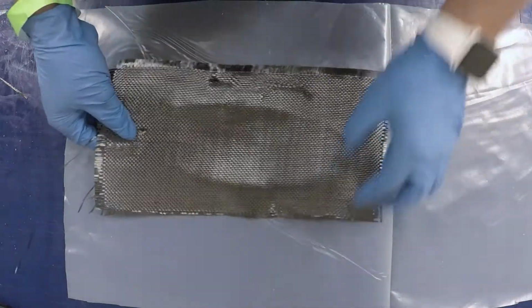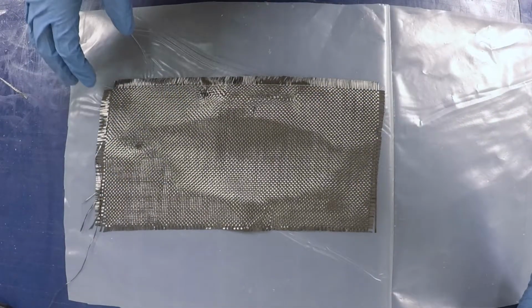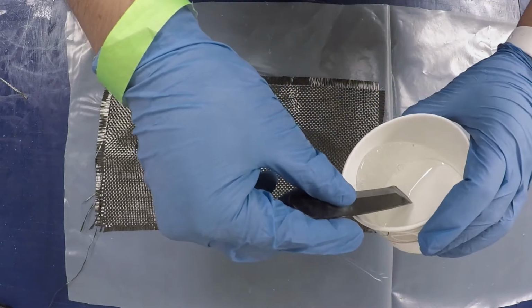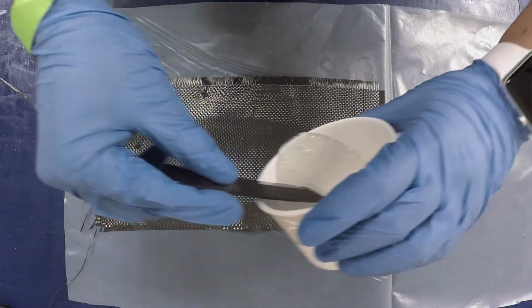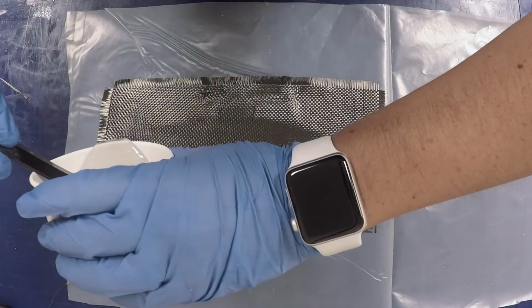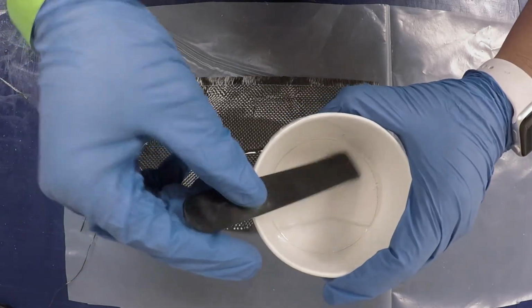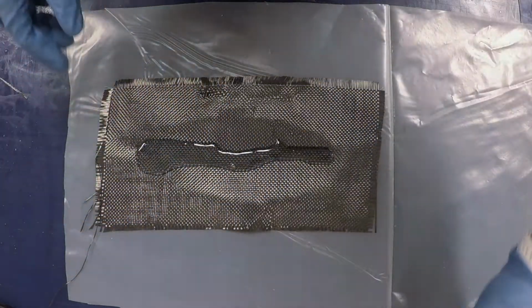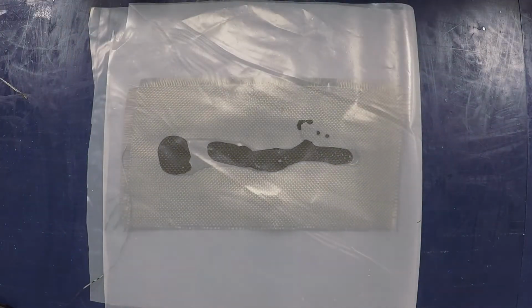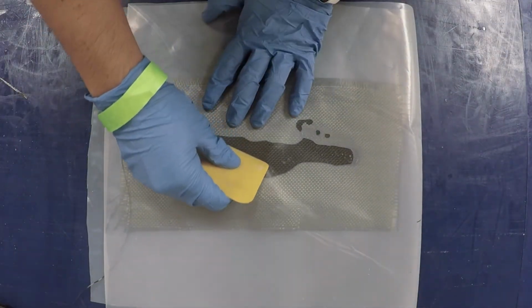Having a homogeneous mixture, you can begin wetting the fibers. Lay the first layer of fabric on the plastic and pour some epoxy over it. Having done that, fold the plastic and begin spreading the epoxy with the squeegee.